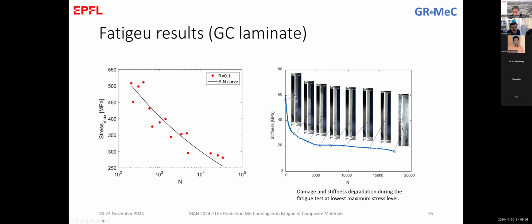We start initially, the first photo is here where we have a more or less intact specimen with only a few whitening on the glass, which is the initiation of delamination. And then if we see a photo at this point where the stiffness has already dropped, this can be attributed to the bilinear behavior that we've seen before, more or less. There is already a quite significant delamination between the glass and the carbon that causes this stiffness drop. This is the same that we've seen in the quasi-static loading.